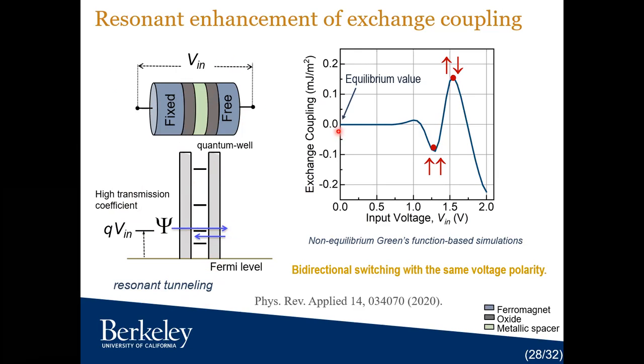What we found is that yes, it's possible to induce a voltage controlled exchange coupling energy that oscillates as a function of the voltage. If you apply this much voltage, you will induce a positive exchange coupling that will make the two magnets anti-parallel, or if you apply this much voltage, it will make them parallel because this is a negative exchange coupling energy. This is all because of the quantum interference that I was talking about. Once you switch with the exchange coupling and remove the voltage, it will stay that way because the equilibrium value of your exchange coupling is 0. So you can switch in a non-volatile fashion.